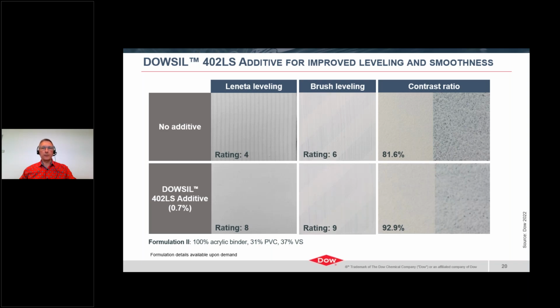sample containing the additive. The middle column shows leveling difference between brushed samples, in this case again with better leveling observed for the sample incorporating the additive when compared to the control. And in the last column on the right, we can see the improvement in contrast ratio for roller applied paint on a contrast chart, with a significant improvement in the value of the contrast ratio, which translates to better applied hiding.